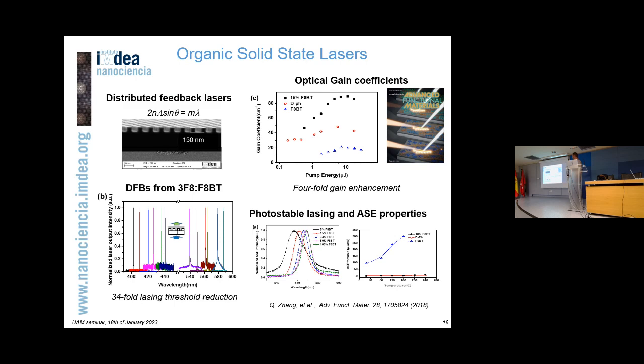This works as a cavity. So when you do that, you can basically pump it, and depending on the different separation of the grooves, you can obtain emission at different wavelengths. You can tune from 540 up to 580 nanometers for the green emitting blends, and this is for the host polymer only, for F8BT. It works quite well. We get nice optical gain coefficients, much higher in the blends than in the pure films, and very stable properties. Everything works quite well.